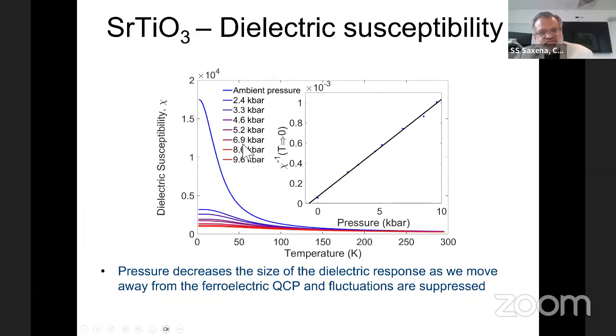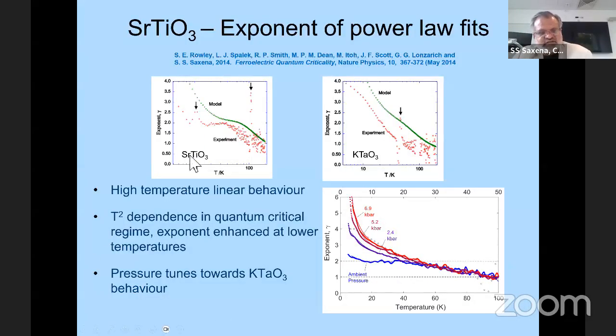So with a very small pressure, you can see you can collapse this very high, what is known as the quantum paraelectric susceptibility. Strontium titanate does not order, as I mentioned, by itself, but if you apply pressure, you push it away from the quantum critical point. And what is even more exciting is that if you take the power law, you can see how it persists up to nearly 40 Kelvin in a quantum critical state. And those who make devices and other things, and bolometers, should be aware of this. This thing is lurking underneath the surface and causing new couplings.